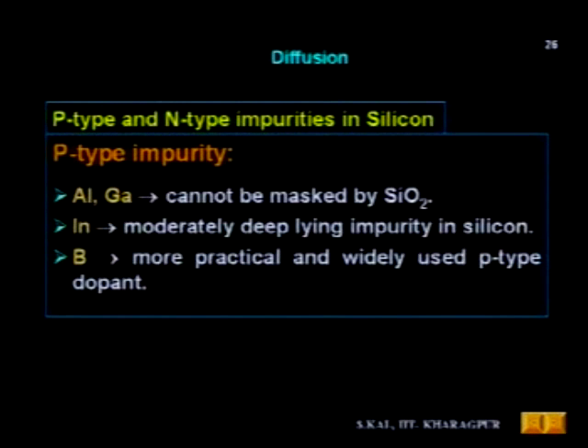Of those two materials, one of the major problems is that they cannot be masked by silicon dioxide. We know that during the diffusion process the entire surface of silicon is not doped with the dopant; a selective portion is doped, and other portions are masked by silicon dioxide. Silicon dioxide is a common masking material in VLSI processing. The masking property will be lost if the diffusivity of the impurity atoms in silicon and silicon dioxide are the same, or if the diffusivity of the dopant atom in silicon dioxide is more compared to silicon.